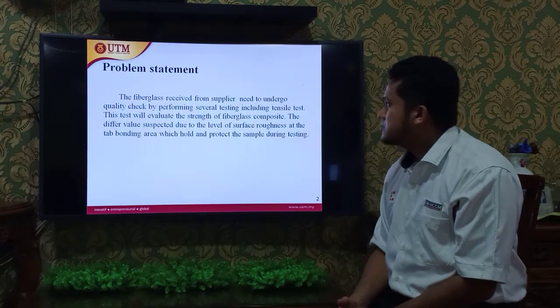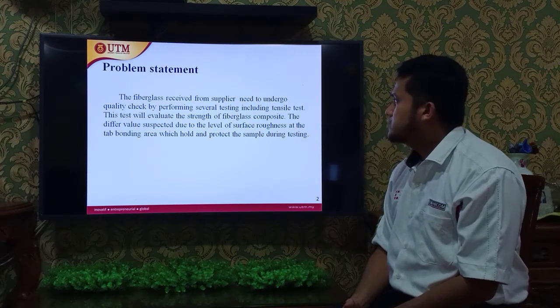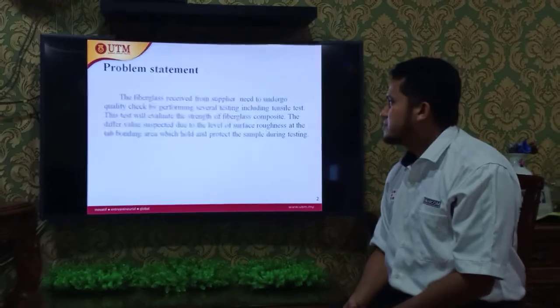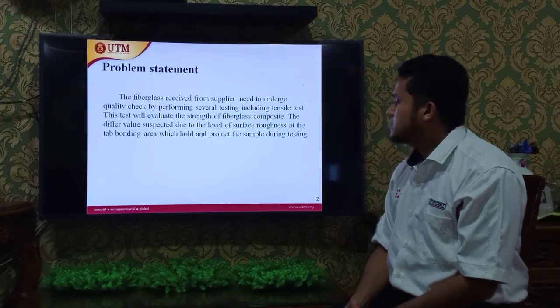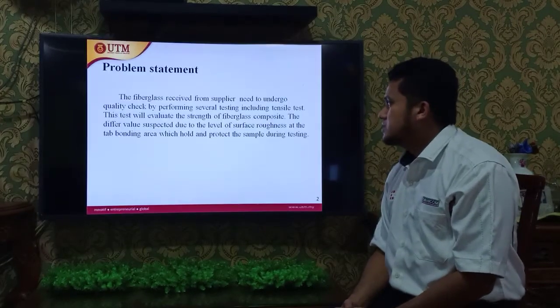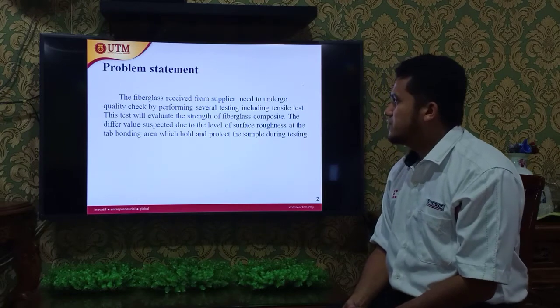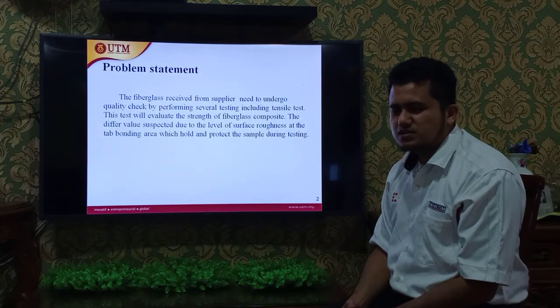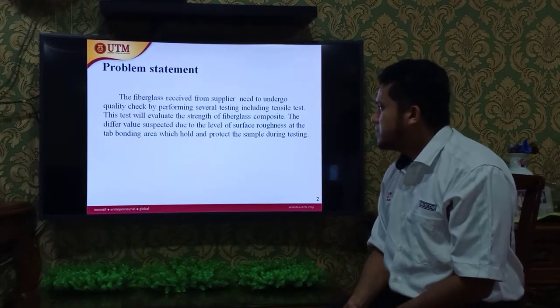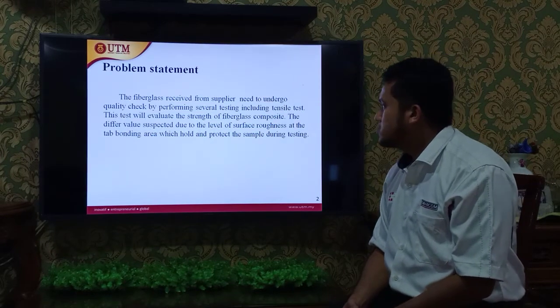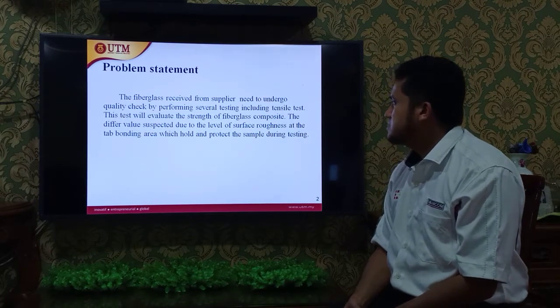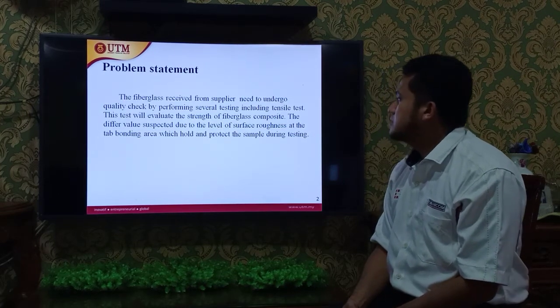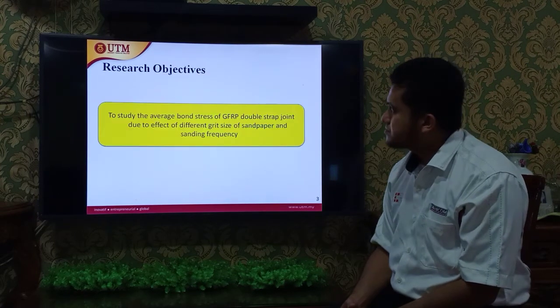The fiberglass received from the supplier needs to undergo a quality check by performing several tests, including a tensile test. This test will evaluate the strength of the fiberglass composite. The differing values are suspected to be due to the level of surface roughness at the tab bonding area, which holds and protects the sample during testing.